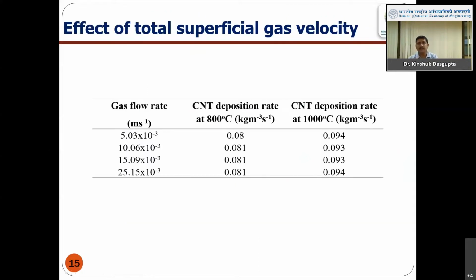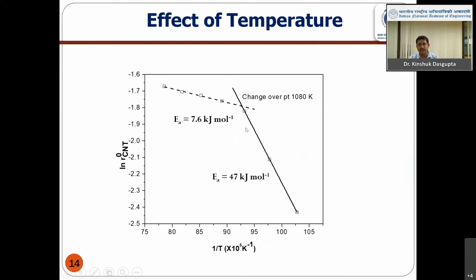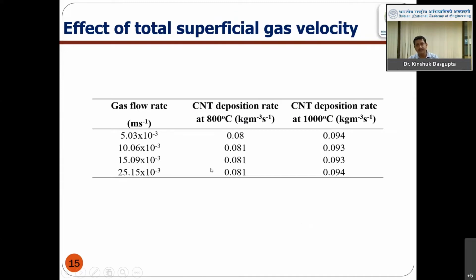Now, as I discussed, we changed the superficial gas velocity in the two regimes, both at 800 degrees, if we go back to the previous slide. So I am considering these two regimes, the right hand side one and the left hand side one. I am carrying out experiments in both regimes, and if I see the carbon deposition, CNT deposition rate, it is not getting affected in both temperature ranges. So we can conclude that external diffusion is not the rate controlling. That is why there is no effect on the carbon nanotube deposition rate at these temperatures.